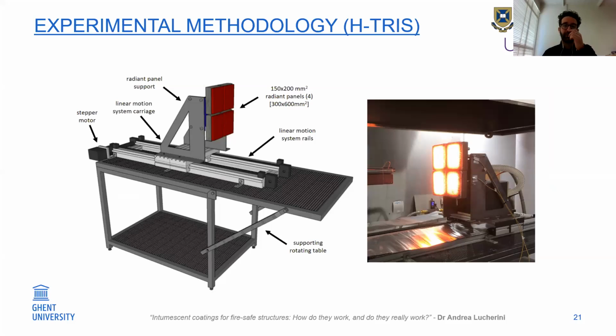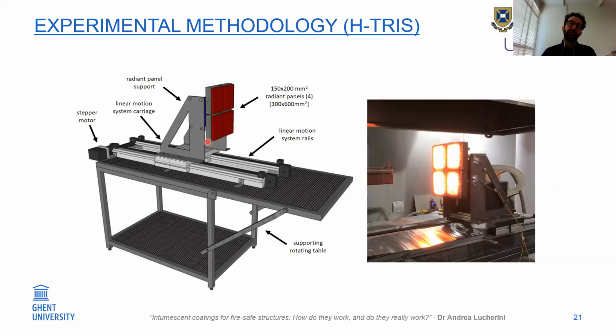The first one that I showed you previously was version 1, and then this is version 2, which has, instead of the single radiant panel I showed you earlier, 4 radiant panels. They have a total radiant area of 300 by 600 square millimeters. You can see that the radiant panel can move back and forth on this linear motion system using a stepper motor, and this is also based on a rotating table.